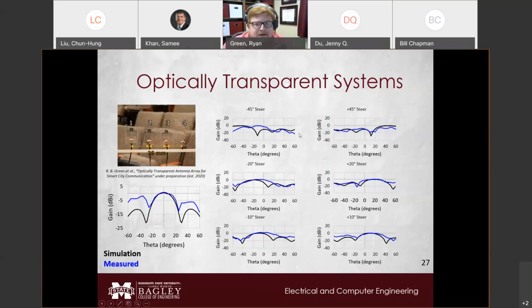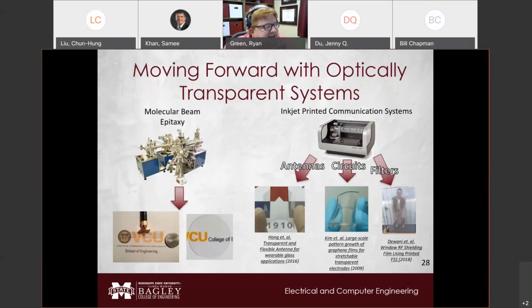And that leads me to another challenge with these optically transparent antennas, and that's really the way that they're fabricated. So these antennas and frequency selective surfaces were made using molecular beam epitaxy, or MBE, where you take a sapphire wafer and you grow your oxide layer by layer, and then you etch it away. In total, it takes about 16 hours per antenna or per wafer to get what you want. And then you have to physically hand score it, which could possibly cause damage to the antenna just to get to the point where you can test it.